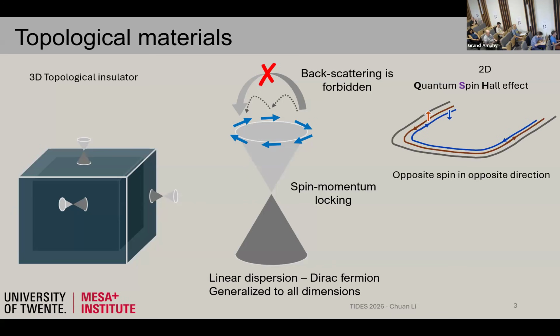In this case, it's also called the quantum spin Hall effect. Here there are no other choices; the two edge modes have to backscatter into each other, which is a much more strongly suppressed process. So in some aspects, these lower dimensions give you stronger protection of your topological states.